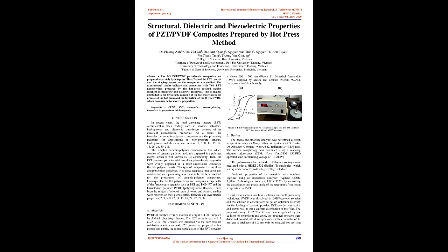The experimental results indicate that composites with 70% PZT nanopowders prepared by the hot press method exhibit excellent piezoelectric and dielectric properties. This is mainly attributed to the favorable coupling of the two materials in the process of the hot press and the formation of the β-phase PVDF, which possesses better electric properties.